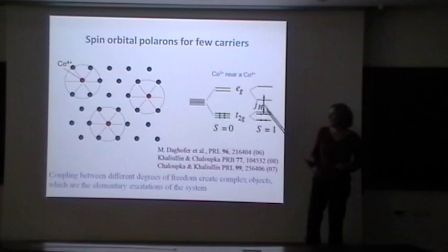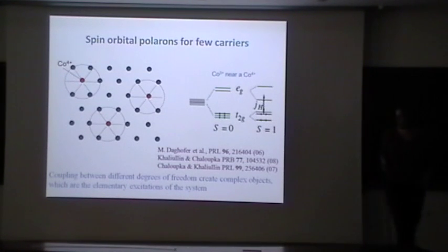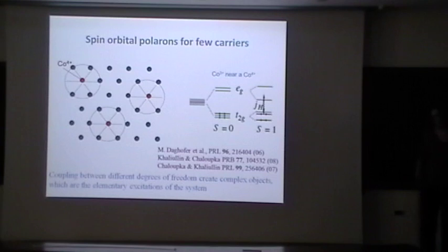Yeah, so in this family, in the bismuth cobaltate, for example, it's known that at high temperature, about 300 K, you can see in the susceptibility some anomaly. It can also be explained by the transition of cobalt 3 plus from low spin to high spin. So these states are not very far in energy, but it's still a question whether they can really be important for these states or not.